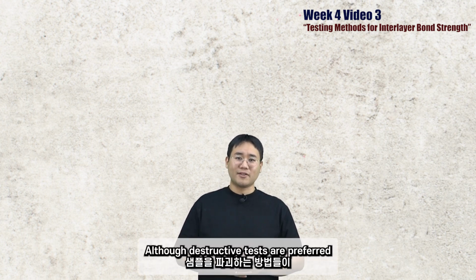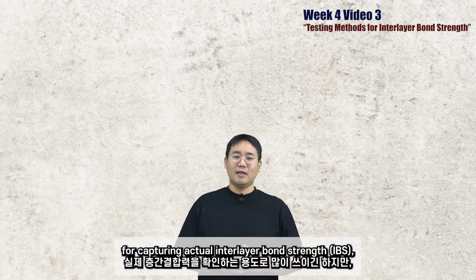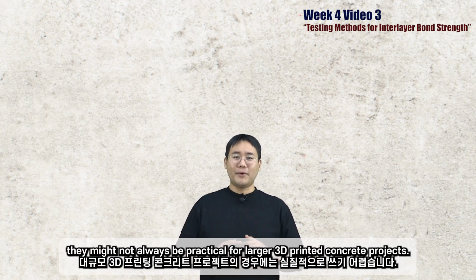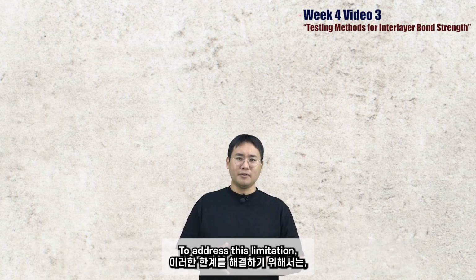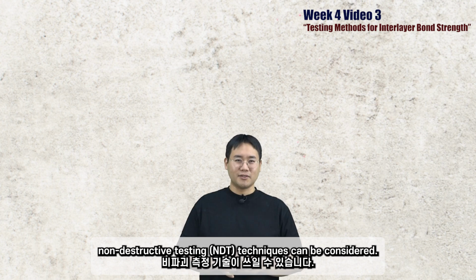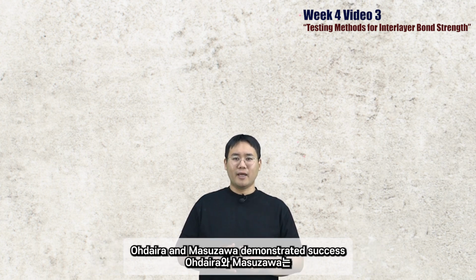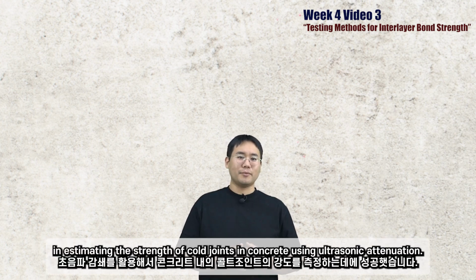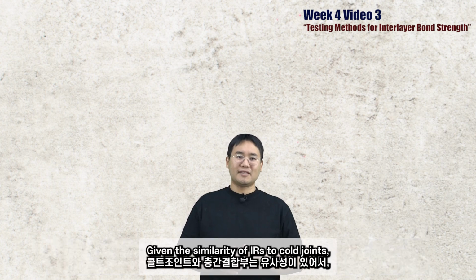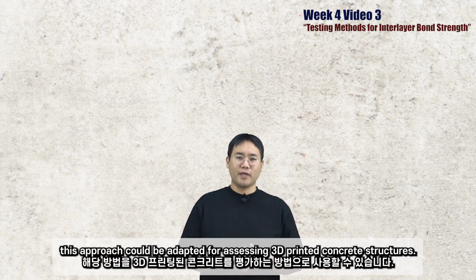Although destructive tests are preferred for capturing actual interlayer bond strength, they might not always be practical for larger 3D printed concrete projects. To address this limitation, non-destructive testing techniques can be considered. Ohdaira and Masuzawa demonstrated success in estimating the strength of cold joints in concrete using ultrasonic attenuation. Given the similarity of interface regions to cold joints, this approach could be adapted for assessing 3D printed concrete structures.